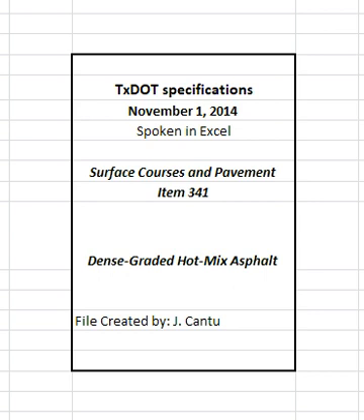The engineer will designate the plant or the quarry as the sampling location. Provide samples from materials produced for the project. The engineer will establish the surface aggregate classification, SAC, and perform Los Angeles abrasion, magnesium sulfate soundness, and Micro-Deval tests. Perform all other aggregate quality tests listed in Table 1. Document all test results on the mixture design report. The engineer may perform tests on independent or split samples to verify contractor test results. Stockpile aggregates for each source and type separately. Determine aggregate gradations for mixture design and production testing based on the washed sieve analysis given in Tex-200-F, Part 2.